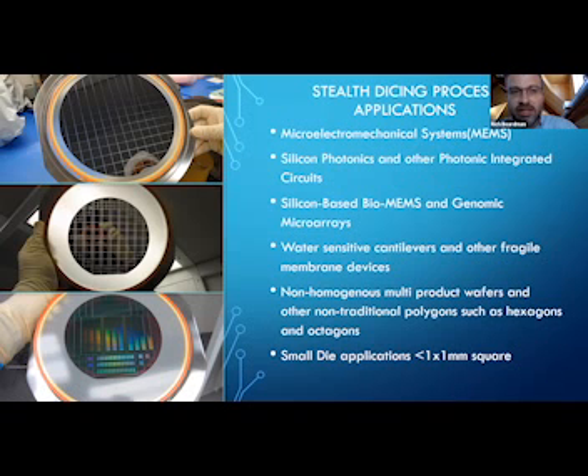So what you're looking at here with these images is after the tape expansion step has been completed, you can see the singulated die on tape. As I mentioned previously, there's no water. This is a completely dry singulation method. There's no debris that's generated like you would see with a traditional mechanical dicing process. You've got an extremely dry and particle-free singulation process here. For MEMS devices, this was really where the inception of stealth came from in about 2007 and 2008. MEMS devices came along and they had sensitivities to the vibration from the mechanical dicing process and the sawdust that was generated, and that was an absolute showstopper. So having a dry and particle-free singulation method was hugely helpful.